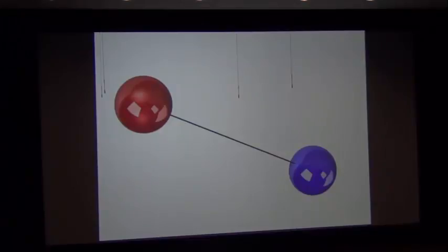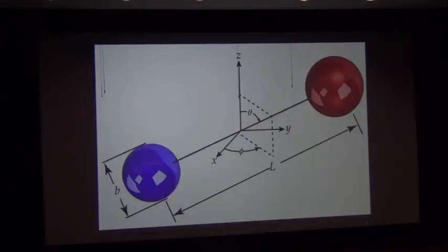That's correct. And so when my teeth were cut on this subject, I was taught that entanglements were important, and that was wrong. What's relevant about a macromolecule is that it is longer than it is wide, and objects that are longer than they are wide have orientation. And for orientation, we need a spherical coordinate system to describe that orientation. That's right, I plan to explain all of the things I've been measuring in terms of the orientations of the molecules. When I talk about molecular motion, I'm talking about the evolution of their orientations with respect to time.